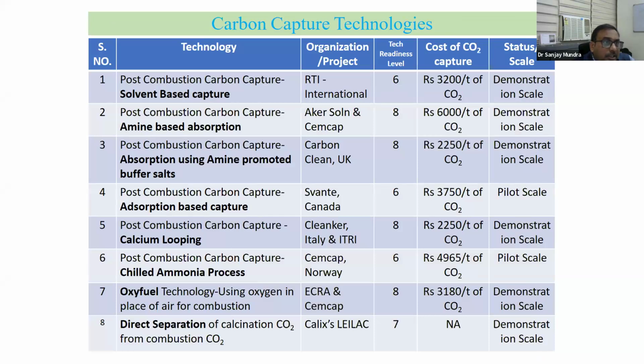Then carbon capture technologies. These are the available technologies worldwide. Post-combustion carbon capture solvent techniques by RTI International. They have gone up to the level of TRL 6, and the cost of CO2 capture is around 3,200 per metric ton of CO2. And they are already demonstrated at a scale. Post-combustion by amine-based absorption by Aker Solutions and Cemcap. They have a TRL level of 8. The cost of CO2 is 6,000 per ton of CO2 at a demonstration scale.